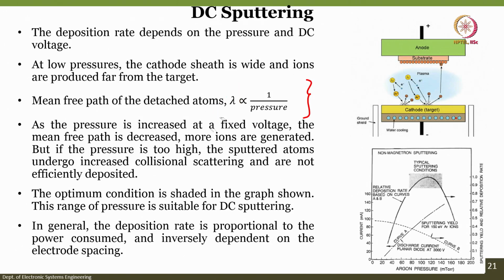As the pressure increases at a fixed voltage, the mean free path is decreased and more ions are generated, but if the pressure is too high, the sputtered atoms undergo increased collision scattering and are not efficiently deposited. If the pressure is too high, the mean free path would be less, and instead of depositing onto the substrate, they will just collide with each other and form scattering. If there is a lot of scattering, that means the deposition would not be uniform and also not efficient.